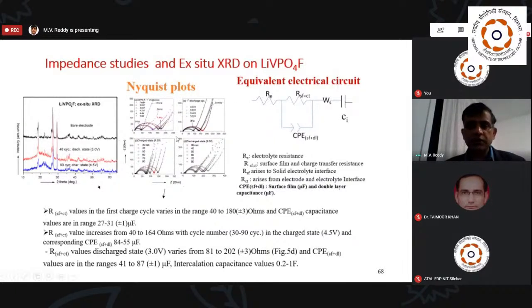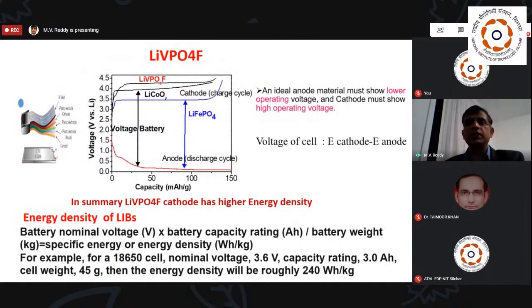Here you can see the voltage with respect to cycle number, and we check whether the material is degrading or not. So this is the way for long-term cycling, etc. In summary, why we are famous: compared to lithium iron phosphate and other commercial vanadium-containing compounds, this is reasonably good, because here from 3.2 volts we get nearly 4 volts, an improvement of nearly 0.5 volts or more. Automatically we get more energy density when compared to lithium iron phosphate.